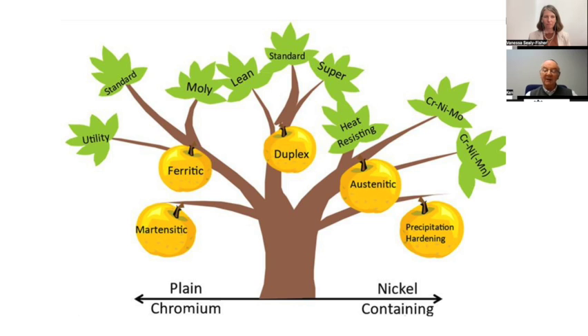A second benefit, and that manifests itself in a life cycle cost type calculation, is that when it comes to being able to cope with operating stresses. So, for example, if you have rotating equipment and you have high stress being imposed while the equipment is rotating, very often you would be outside the approved limits for an austenitic material. Whereas with a duplex material, the chances are you might be within the design limits for the material. So that's another advantage. And furthermore, you might be able to down gauge the thickness of material. So that would mean that your drive system and everything that goes with it could be specified accordingly.